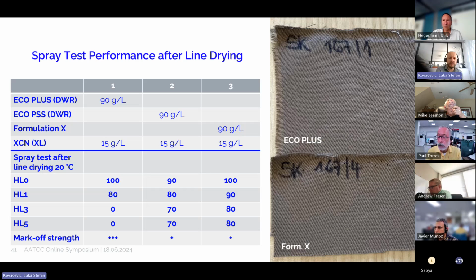What we are working on at the moment is a combination of this Eco PSS, that product that has been created against chalk marks, and we are looking for a solution that at the same time provides the water repellent performance of an Eco Plus. Here you can see in this graph, the spray test of Eco Plus finishes yields a 100, no problems. Our Eco PSS can achieve a 90 only, sometimes even lower on particular fibers. These are spray test figures after line drying.